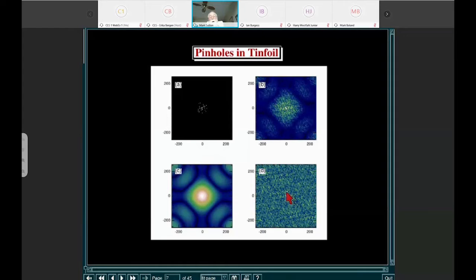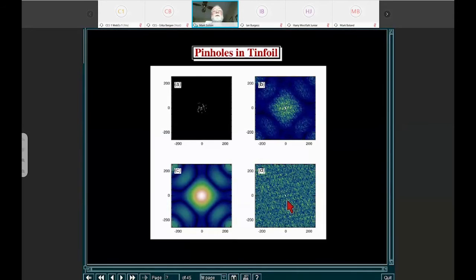The condition for getting that is that the coherent fraction of the X-rays in the diffraction volume is a high fraction of the number of X-rays in that diffraction volume. As soon as you do that, you'll see speckle patterns. If you had single crystals, the speckles will basically be the size of the Bragg peaks, and the Bragg peaks will have a shape which is 2 pi over the shape of the sample. In some sense, that's partially what's being done with coherent diffraction imaging, looking at the shapes of Bragg peaks to understand what nanoparticles do. Why am I interested in it?